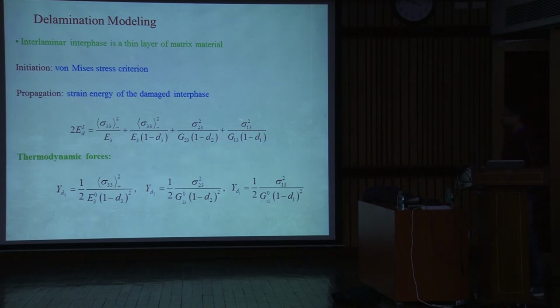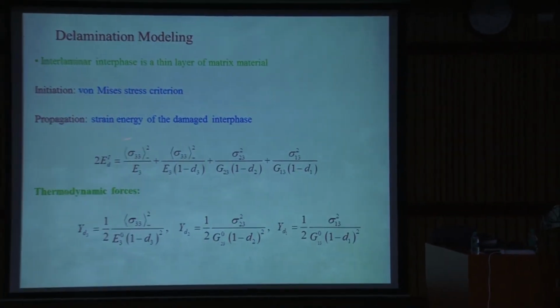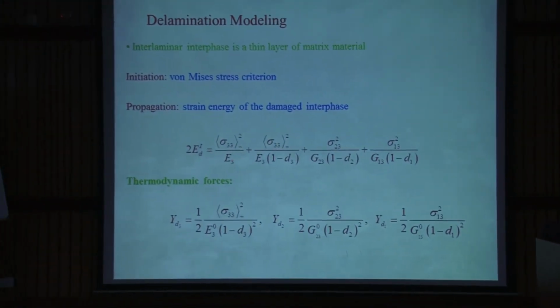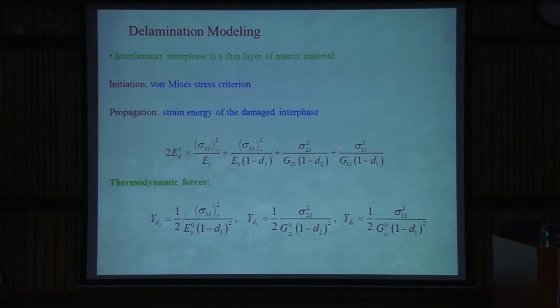But for the propagation also, what we are doing is defining the strain energy of the damaged interface. In this case, you will have the damage propagation for the delamination in 3 modes. Mode 1, the opening mode, then mode 2, and mode 3, the sliding modes. So for each mode you have a different indicator. In the opening mode, it is assumed that the crack, or the delamination, will propagate only when the stress is tensile. If it is compressive, then no damage develops. So this is the strain energy of the damaged interface.